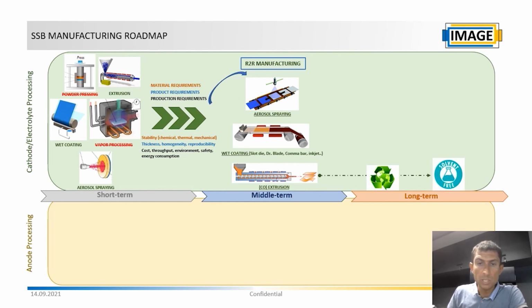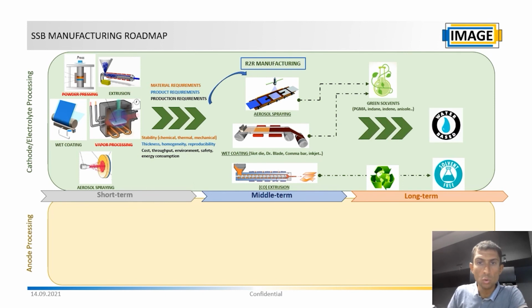Co-extrusion is a very promising approach for the mid and long term since it doesn't make use of solvents, while for wet and aerosol spraying, we would need additional developments to make active materials soluble or dispersible in green solvents and eventually water. I put active material functionalization here and here, but it's very important to remind that it's exactly the active material functionalization that enables wet coating. Nowadays, most of the efforts are focused on making oxide and sulfide electrolytes soluble or dispersible in organic solvents in order to be able to wet process them.